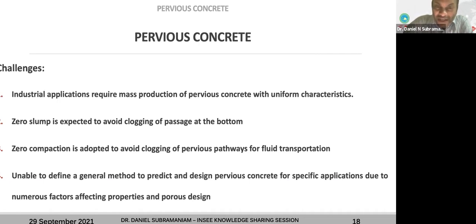As I said, zero slump, which I'll be talking about with a picture later on. We need to have zero slump, or even probably around 10 to 15 millimeters of slump, not more than that. And then zero compaction. Again, if you do a lot of compaction, you tend to block the passage of the water, or the connected porosity at the bottom surface. So we need to have almost zero compaction. Most of the studies are with zero compaction, or a little bit of tamping with the tamping rod.